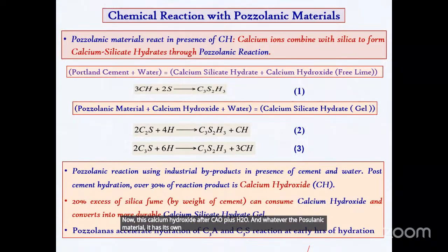own composition. In that, Al2O3, then SiO2 and all. The SiO2 reacting with the calcium hydroxide, Ca(OH)2. So that is what actually: the SiO2 present in the pozzolanic material is not reactive on its own. But in the presence of cement and water, SiO2 will behave differently. So calcium silicate hydrate gel will be formed, in a different form.